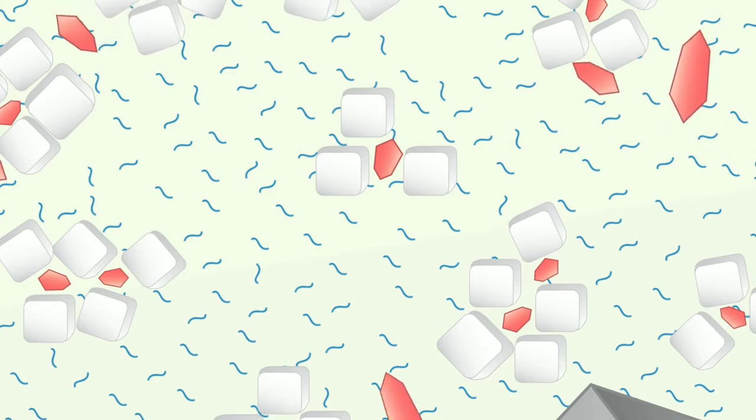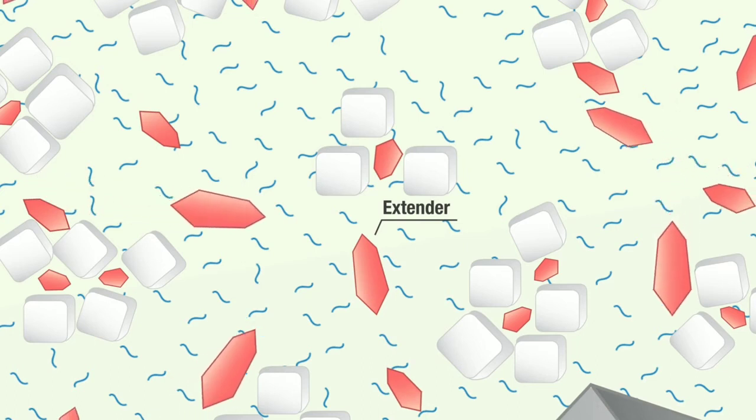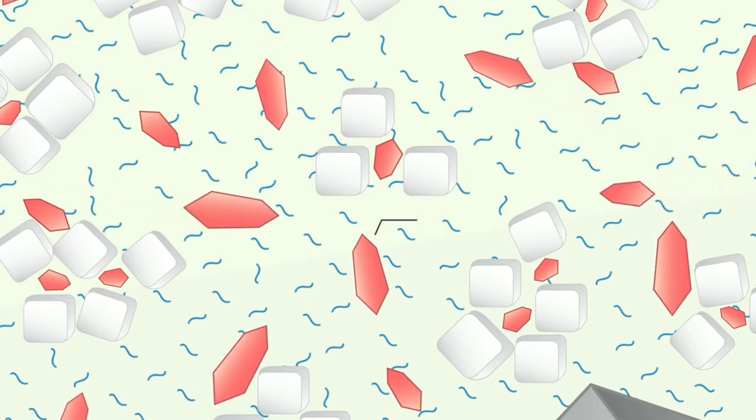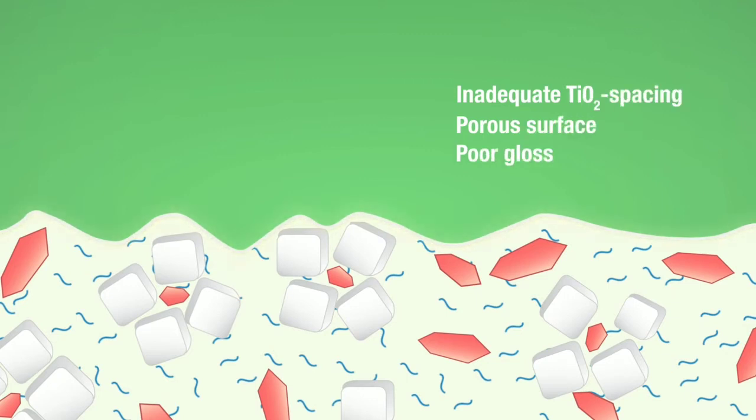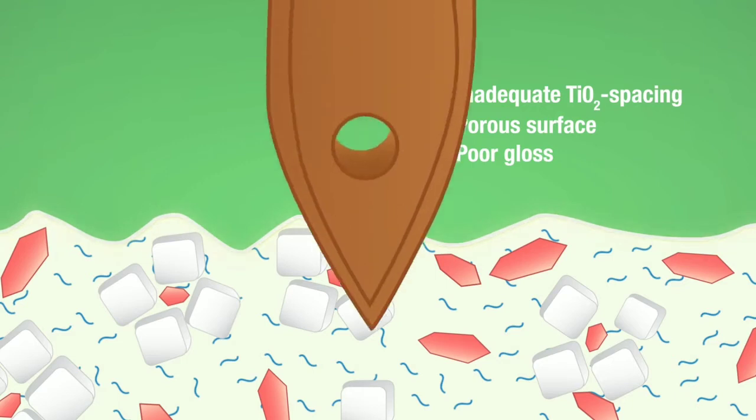A common extender encompasses nanoparticles in addition to large particles, which provokes negative titanium dioxide agglomeration, increasing the tendency to adhere with the pigments. The coarse aggregates damage the smoothness of the paint surface, resulting in poor gloss performance.